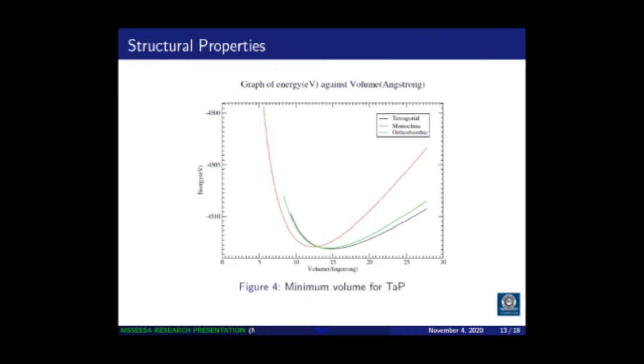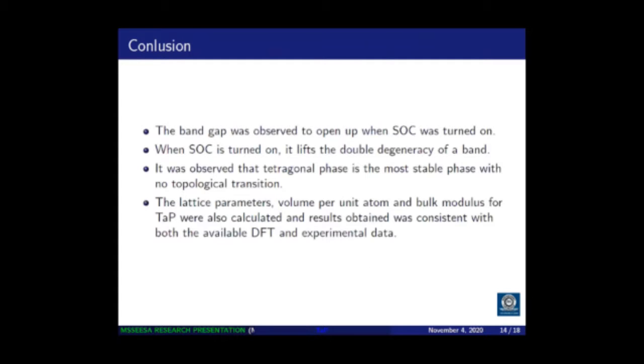So I was able to calculate also the volume for the three graphs so that I get which phase has the minimum energy, minimum volume. And as you can see from this graph, it's the tetragonal phase that has the minimum volume. We can move to the next.